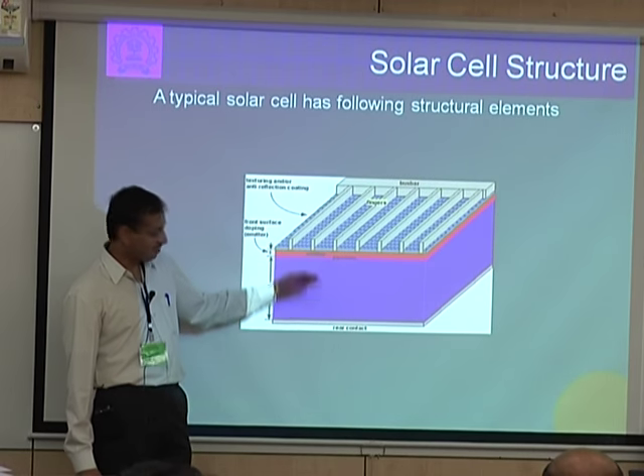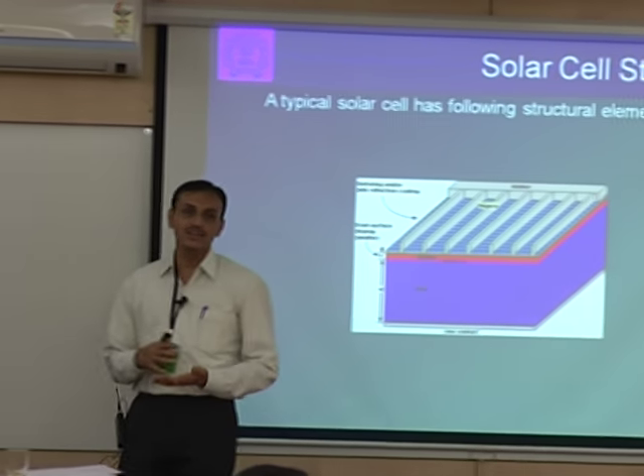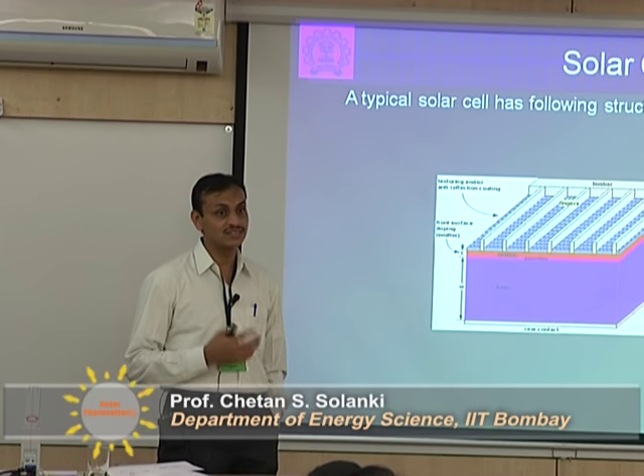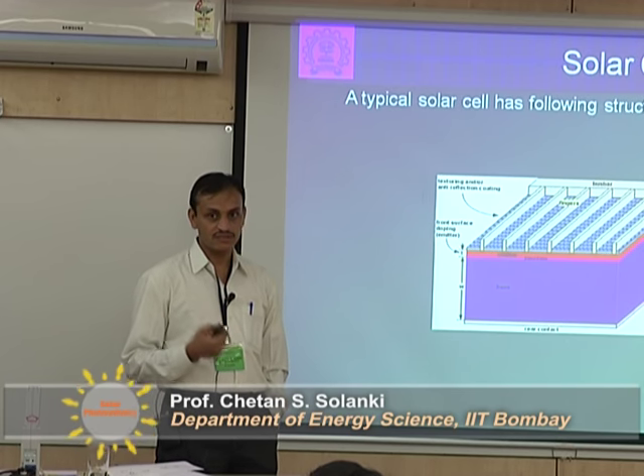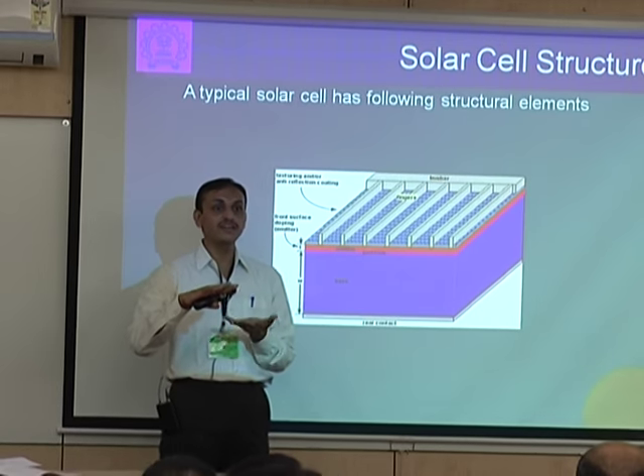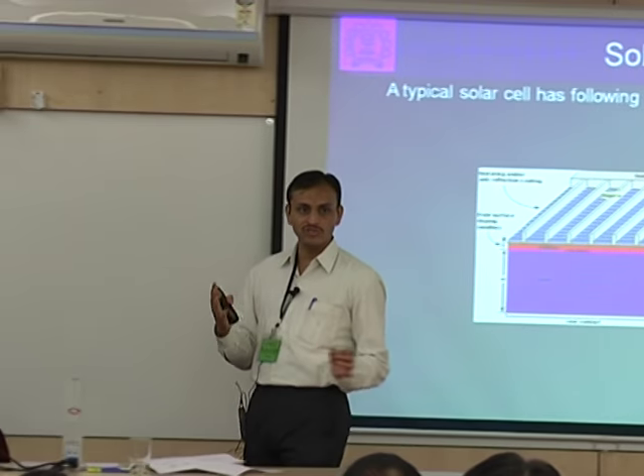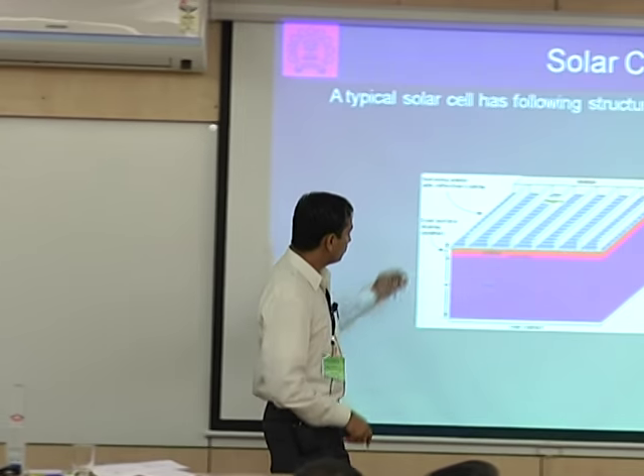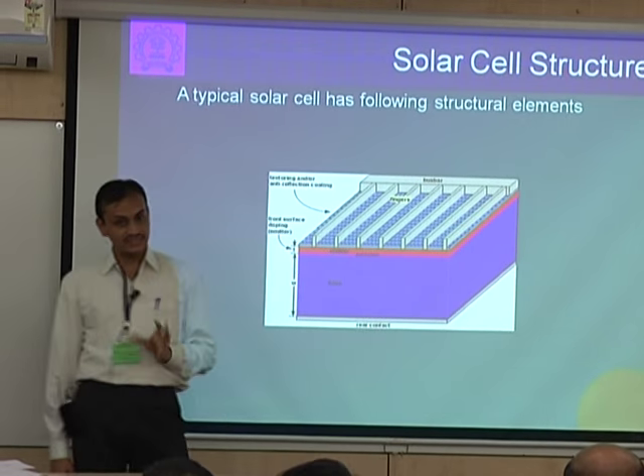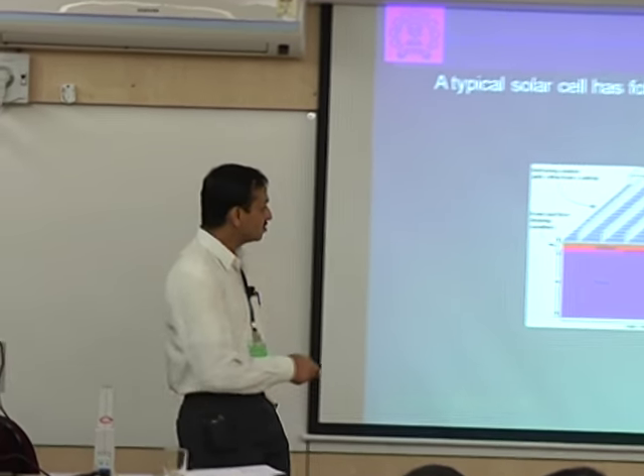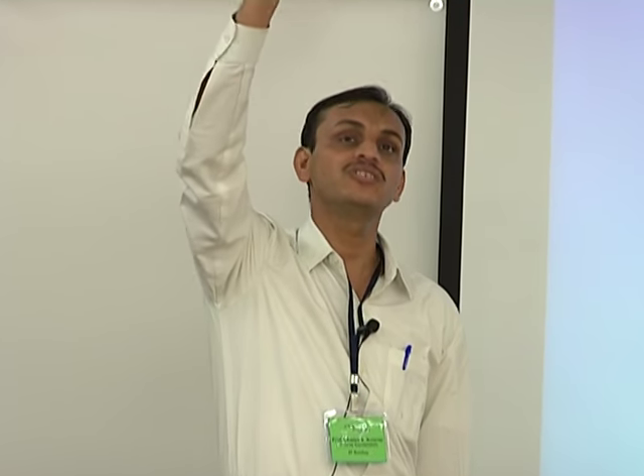The thickness of the silicon wafer nowadays — the industry standard is 180 micron. When I was doing my PhD it was 400 micron, and before that it was 600–700 micron. People are going for thinner and thinner wafers to save cost because silicon is expensive. Within that 180 micron, your junction should not sit at 90 micron — not in the middle. What people are doing right now is making a junction of 300–400 nanometers, and some are going below 300 nanometers — 150, 175, 200 nanometers. That is the junction depth, sitting very thin at the top of the layer.